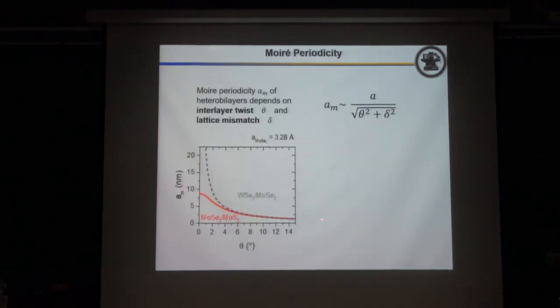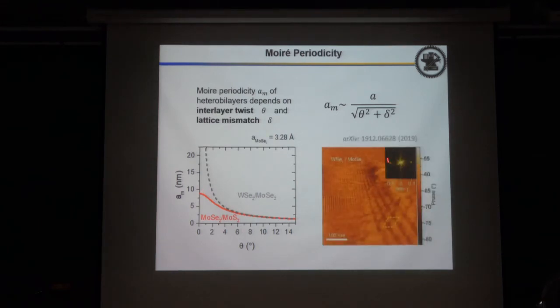So typically the periodicity is inversely proportional to the twist angle, and also the lattice mismatch. So this is the lattice match case. When you use a very small angle, the periodicity can become very, very large. And this is the lattice mismatch case. So if you change the twist angle to 0, it pins the periodicity at about a few nanometers. So this is a typical image of the Moiré pattern.